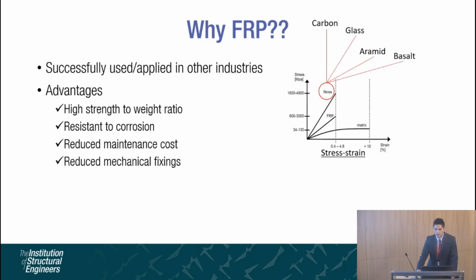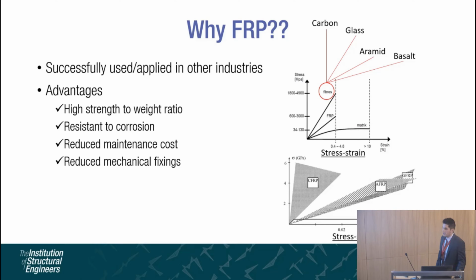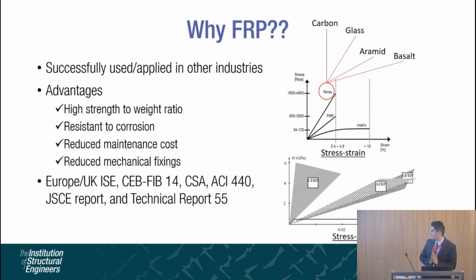Fiber reinforced polymer composites are made of fibers, of very high tensile strength, inside a polymer matrix. A typical stress strain graph for the FRP materials is shown over there. Generally, there are 4 materials available: carbon, glass, aramid, and basalt. All of them have different properties in terms of their tensile strength, carbon being the highest, and AFRP and GFRP being somewhere in the middle. And you can see, in comparison to steel, it is significantly higher. For this research, we have chosen CFRP reinforcement for strengthening purposes, primarily due to its high tensile strength.